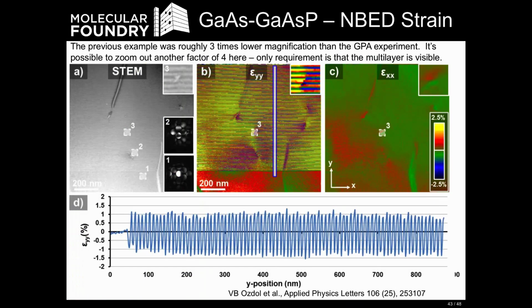Okay, so this is the last plot I'm going to show from here, showing another major advantage. So this is a huge field of view, a micrometer by a micrometer. The conventional image where you look at atomic columns, everything has to be almost perfectly on the zone axis. And the reason is if you can't see the atomic columns, you can't measure the strain. You can't measure their position with high precision. But we're not limited in 4D STEM NBED strain measurements to that type of zone axis alignment.